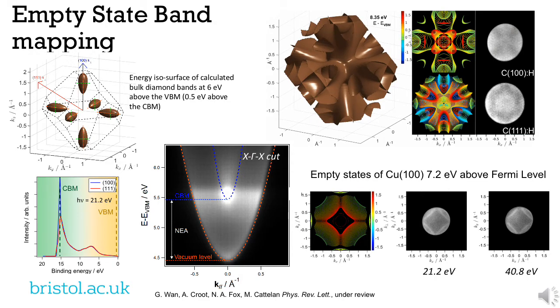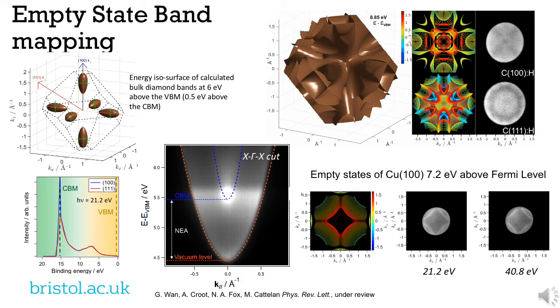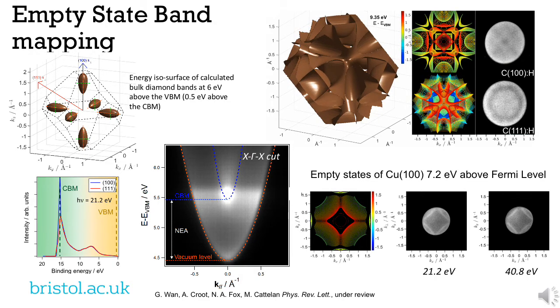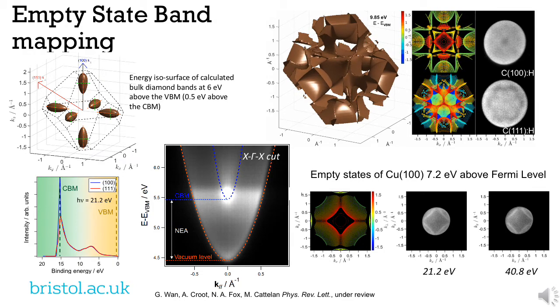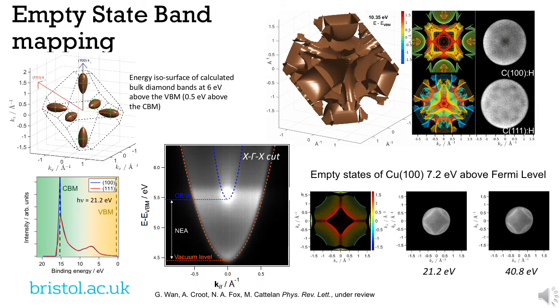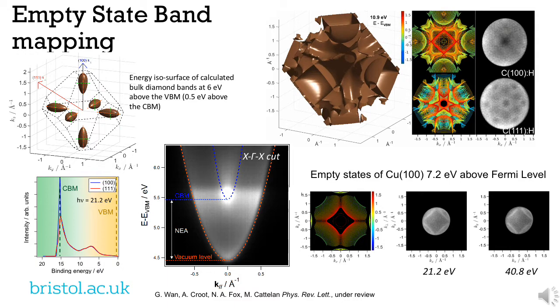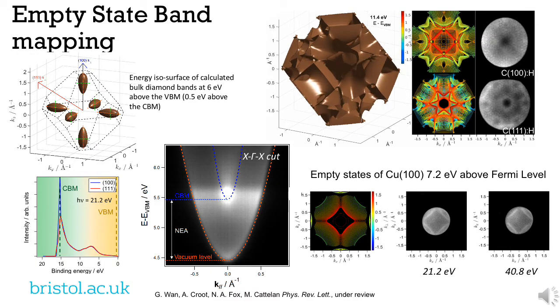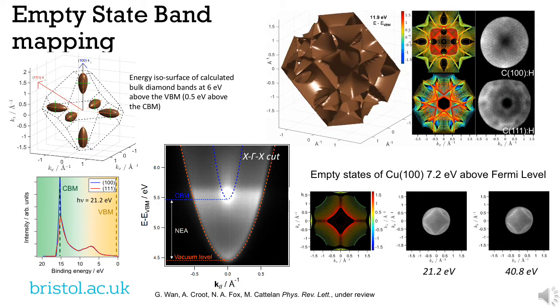Here we show a method to directly observe the unoccupied electronic band structure of crystals using a new interpretation of the low kinetic energy region of photoemission spectra. This region is typically regarded as a secondary electron background containing little